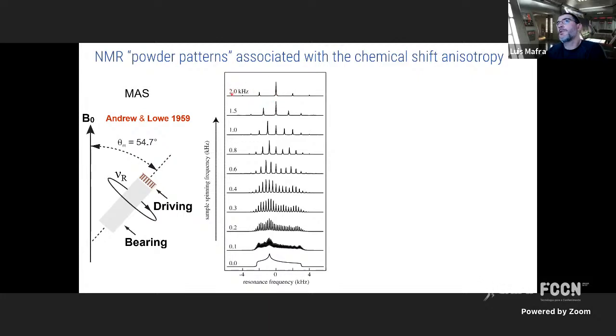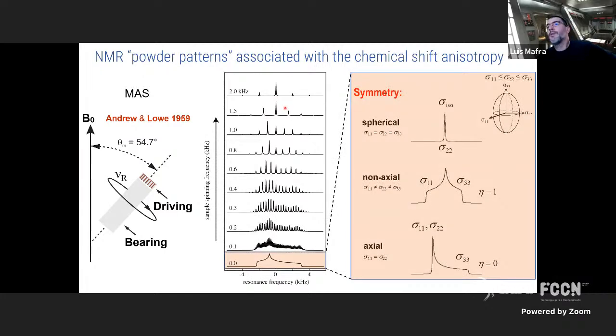You can now spin rotors up to 110 kilohertz. We will not see any spinning sidebands, okay? So you are left with only a single peak if you go to infinite speeds, okay? And that's how you get your isotropic chemical shifts. But keeping our anisotropic chemical shift is also nice, because we have additional information that we cannot access in solution.